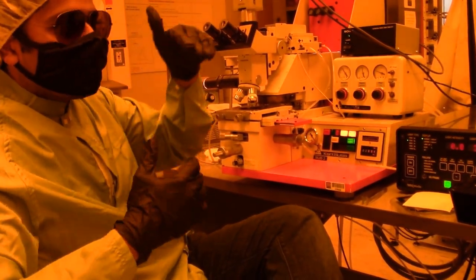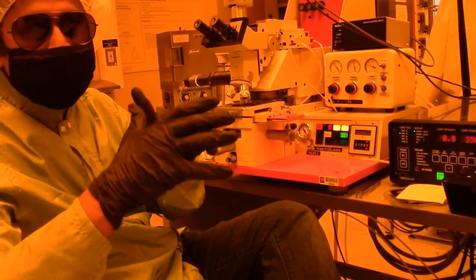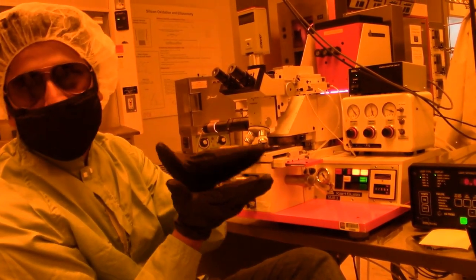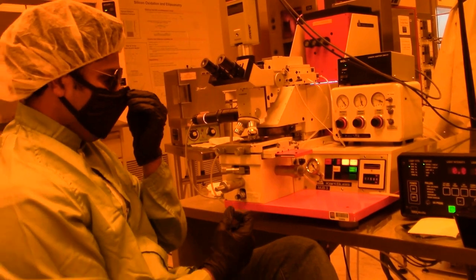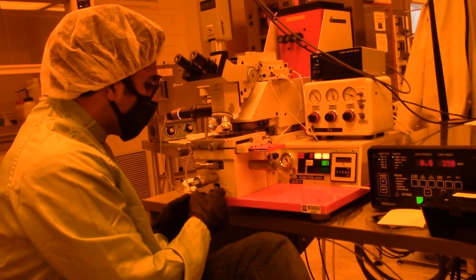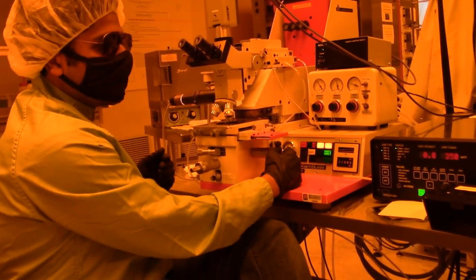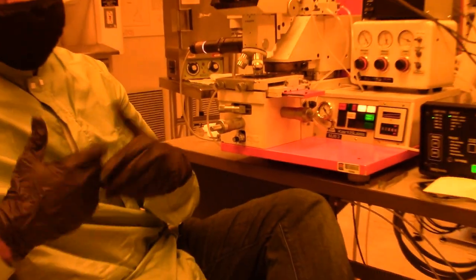So we have a reference pattern under the substrate that we can see, separated from the mask, and we can align our substrate accordingly before bringing them to contact and exposing the photoresist. To make sure it is actually in separation, you need to adjust your Z height so that the mask doesn't move when your substrate is moved during separation. Verify this again when it is in contact. Your mask moves along with your substrate, but when it is in separation, it does not move. When that happens, you are at the optimum Z height to go ahead and do your exposure.